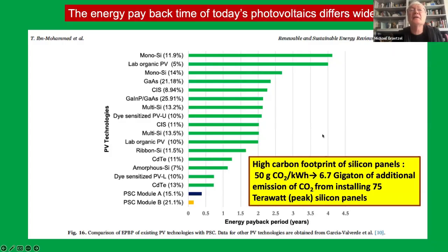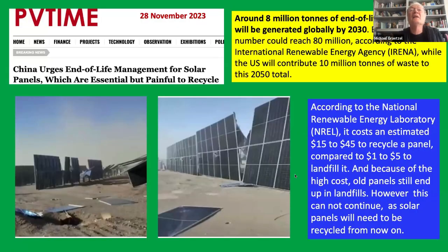This costs energy, so the energy payback time is still quite long, several years for silicon cells, while for the perovskites, for example, it's only a month. We also note the high carbon footprint of silicon. Why is that? To make silicon panels it takes a lot of energy, and how is that produced? Mainly from burning coal, which is highly polluting, so for each kilowatt hour we have 50 grams of CO2 emitted. If we would cover all these 75 terawatts I was showing you with silicon panels, this kind of CO2 release would be many gigatons. And let me remind you, we want to get to zero CO2 emission from currently 40 gigatons per year. There's also the recycling. That's something one has to think about, because there's a tsunami of PV panels that is trying to reach us soon.